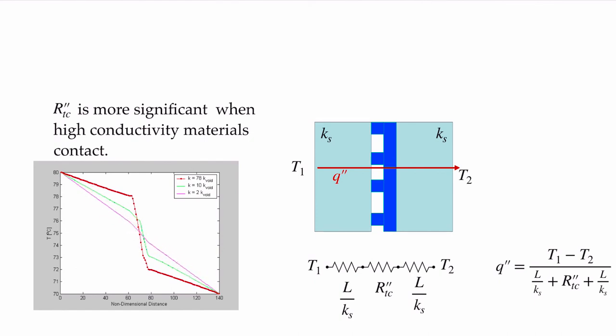So again, to minimize the contact resistance in my copper, I'd want to polish that surface as much as possible to make sure the roughness was as little as possible, and I'd want to contact them with a significant pressure to make as large a contact area as possible. Also, I might want to introduce another fill gas if possible, do it in a different environment than air if it was important, or introduce a thermal paste in order to reduce that. Either way, you can add these to your resistance networks by coming up with a suitable value for the thermal contact resistance and simply adding it into your network as another resistor.